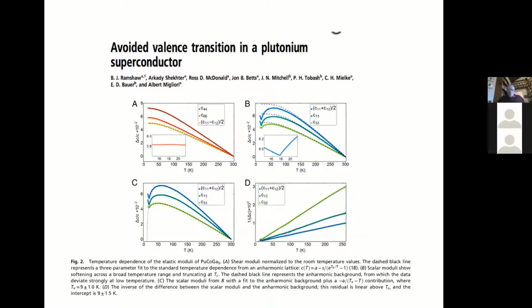ultrasound experiments, and what they discovered is they can extract out what amounts to a kind of bulk modulus from these temperature-dependent elastic constant measurements, and essentially the bulk modulus shows a softening, following the Curie-Weiss type law on cooling to low temperatures. You would have to read the paper to see exactly how they get this data for the bulk modulus from these curves. But you essentially have a Curie-Weiss type law.